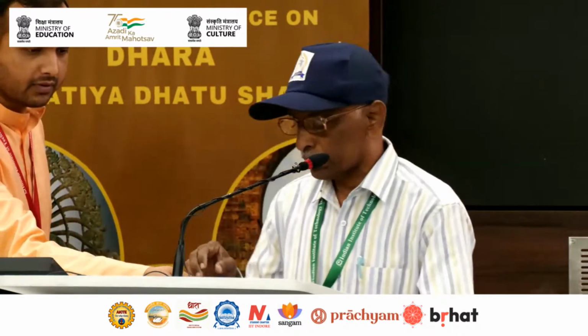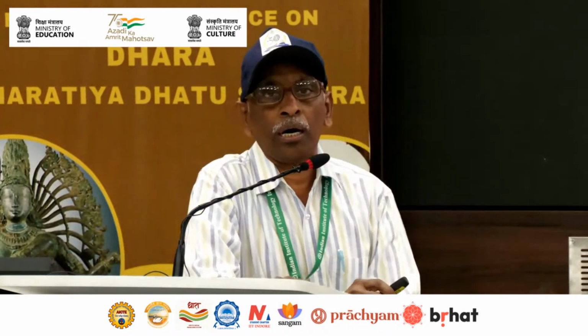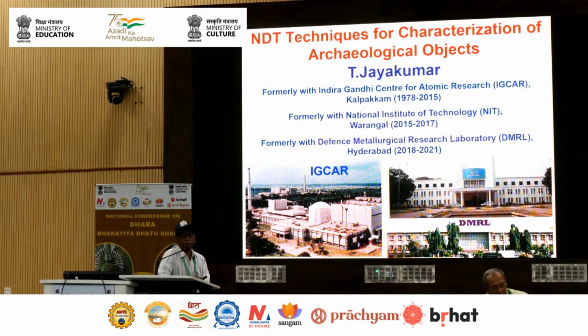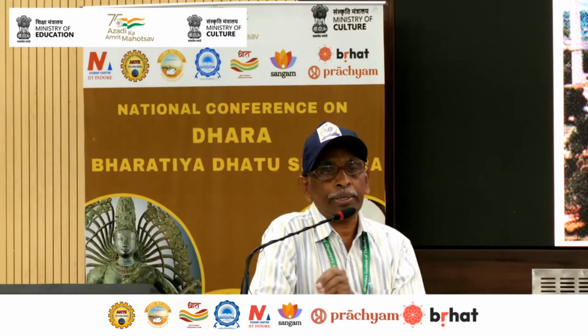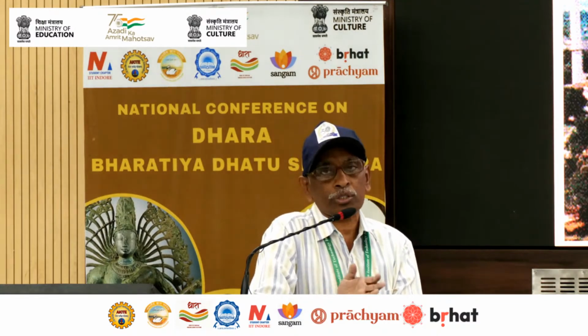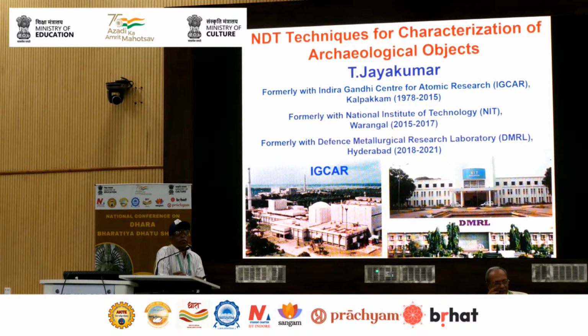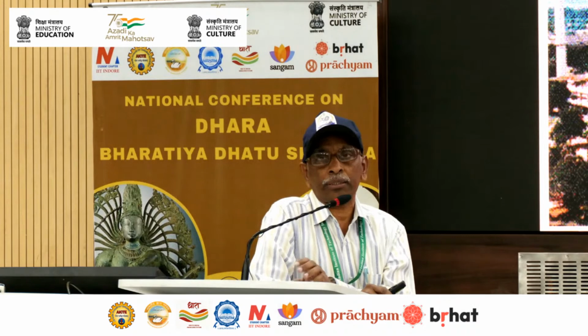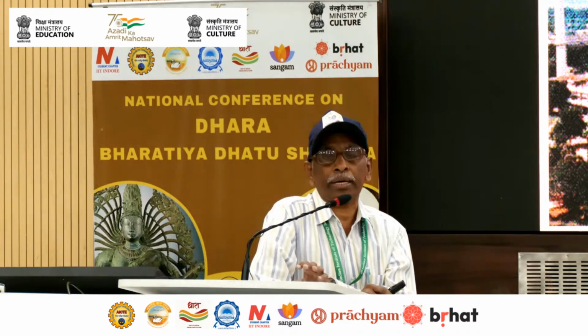And also the thermomechanical processing, it would have gone through at different regions, and the structures what you see through in situ metallography also indicate that the temperatures and strains and the cooling rates, in addition to the composition variation from place to place, would have played a significant role with respect to the microstructures that are generated. But at the same time, I would like to say that the corrosion resistance might not have to do much with the microstructures, rather the phosphorus. And one more point we would like to bring out is that many of the people interpreted on the samples that the needle-like structure, what they see, they consider as phosphorus related. But we also, this is an indirect evidence, not direct evidence, that these are cementite needles.